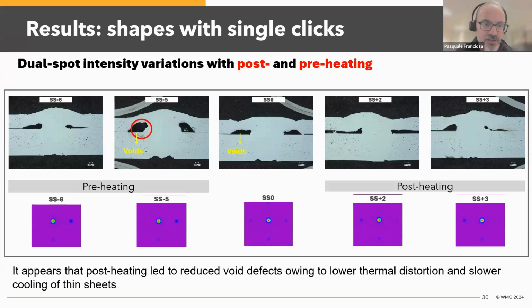Now, if you analyze the cross sections, this was very clear evidence from all those experiments that in the preheating case, we are preheating the material itself, and since the material is very thin, we are only talking 0.4 millimeters, the tendency is to pre-bend before the main spot comes in. This adds a significant void, and those voids are caused by the preheating beam coming in front.